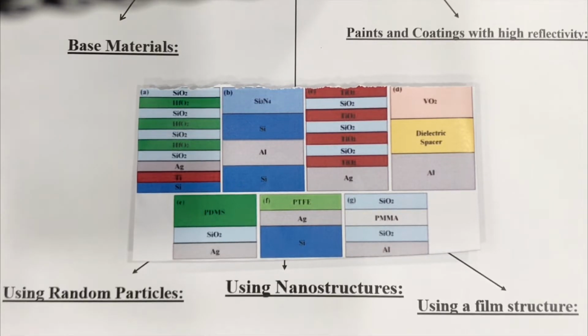researchers designed a film made up of multiple layers of silicon dioxide and titanium dioxide on an aluminum or silver layer, thereby consisting of low and high index materials to utilize their emission spectra and high absorption caused by the phonon polariton resonance. Using this simple, easy to manufacture layered film design, the ability to lower the temperature 5 Celsius below ambient temperature using a radiative cooler power of 100 watts per meter squared was demonstrated.